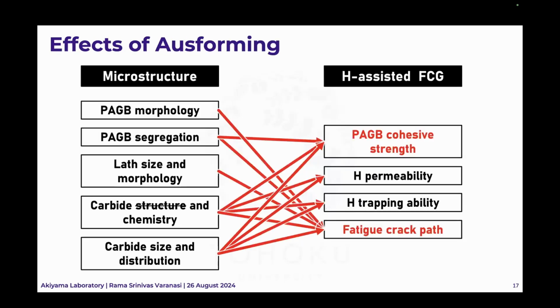So we realize that there's a change in the fatigue crack path, and this also means there's a change in the cohesive strength of the prior austenite grain boundary.